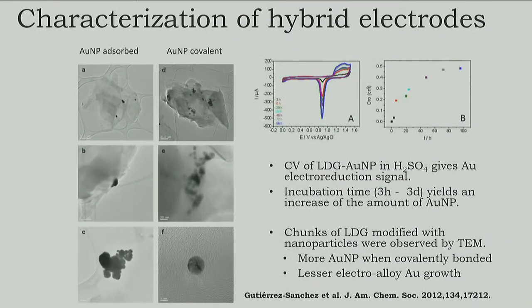So we can see here, this is a part of the electrode that we strip away from the surface, and what is the difference when we have the covalent bonding and the absorbed nanoparticles. We can see that the population of gold is higher, and also after making these activation cycles of gold, we can see here this is a carbon electrode modified with gold. The typical signal of gold appears on the carbon electrode, and the longer we put the nanoparticles on the surface, the more concentration of gold we get. So this peak here, that is gold oxide reduction, is increasing.